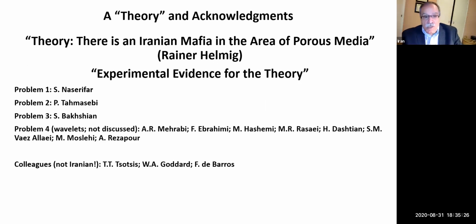And finally, the paper that I showed you was published last year in Transport in Porous Media. We did the problem in which you start with a totally unstructured or totally random computational grid, which, as far as I know, nobody has actually been able to upscale. Based on wavelet transformation, we developed a method which upscales the irregular grid to a coarser irregular grid, and therefore we can simulate this.